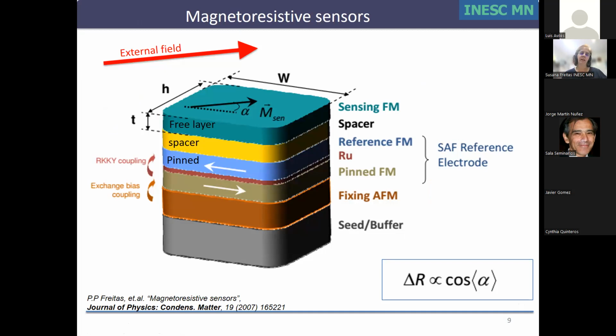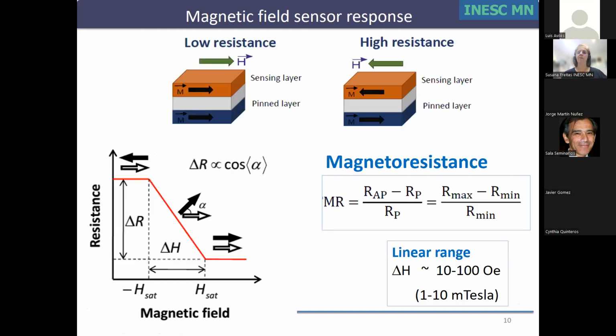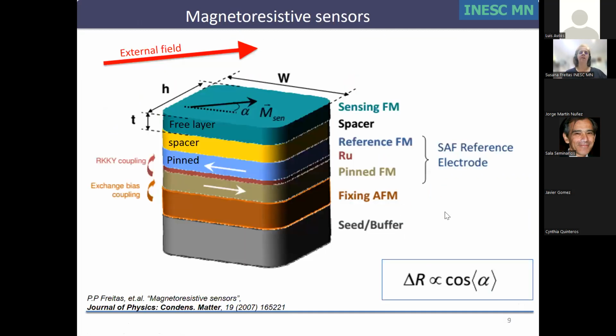What they have in common is a spacer, either copper or a tunnel barrier oxide, but then they have the free layer, which is our sensing layer. And in both structures, they have a pinned layer, which is a reference layer to be used as a reference when we monitor the angle of the free layer. And this is how the sensor should work.